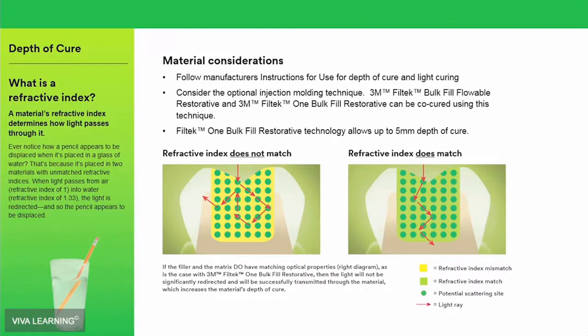I like to call it transitional translucency, all right? So when you put the composite in the tooth, it's more translucent, which is great because that allows the light to penetrate through the material to a full 5 millimeters depth of cure, but then as it polymerizes, it gets this mismatch. So it has transitional translucency. And so when it's done light curing, it is beautiful.